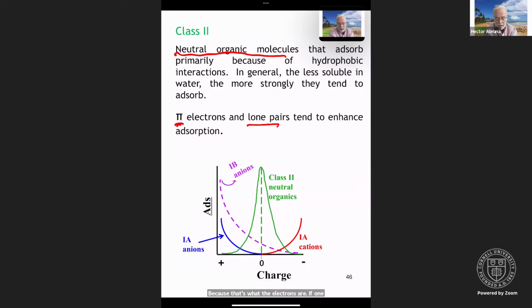If one looks then at what would be the profiles of species as a function of applied potential and, let's say, coverage on the surface, we start with the simple ones. Remember 1A, that these are species that only interact with the electrostatic field at the interface. So here we're plotting the amount of adsorption versus the charge on the electrode surface. So you can start with a neutral surface, positively charged, negatively charged. If we look at the class 1A ions, so here we look at the cations, when the surface has a net negative charge, we see that the concentration of the species goes up. On the other hand, for 1A anions, if you charge the electrode surface positive, then basically it comes up.